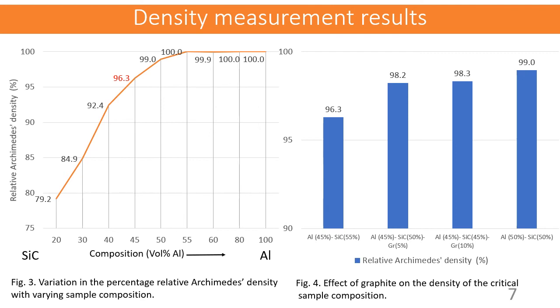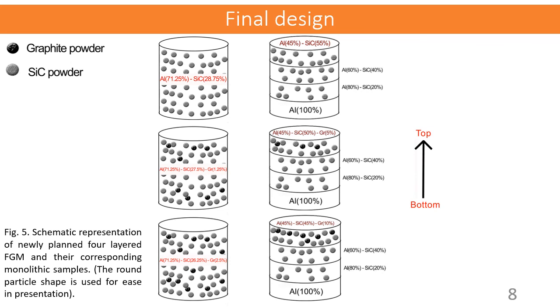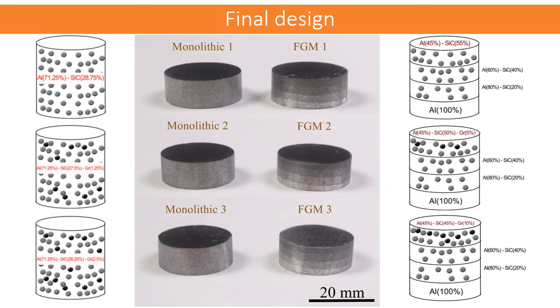So depending on the initial understanding, we prepared a final design where we wanted to fabricate three different functionally graded materials, where the top layer composition is different with and without graphite. So the layer average of all the four layers was designated to the monolithic sample so that we can relatively compare the behavior of the monolithic and FGM sample. So these photos are of the final sintered polished samples where you can easily see with the naked eye that the stepwise gradient is observed, while there is a single composition for the monolithic sample.